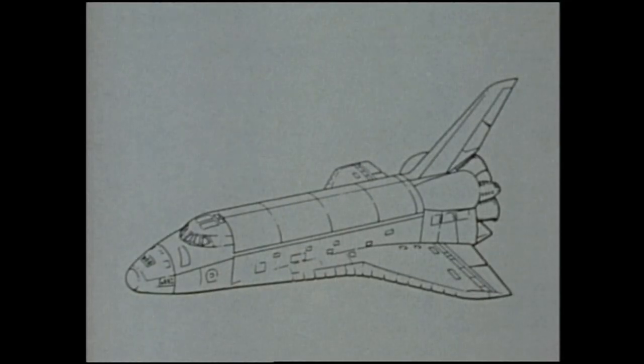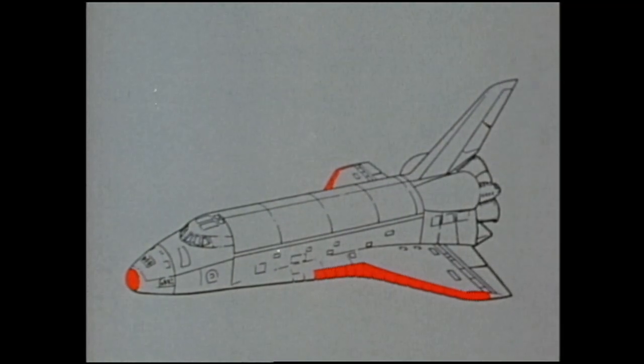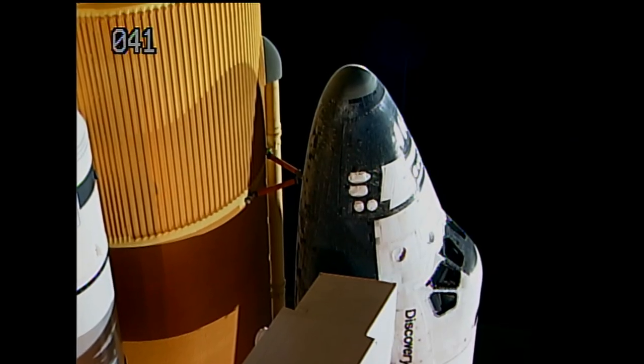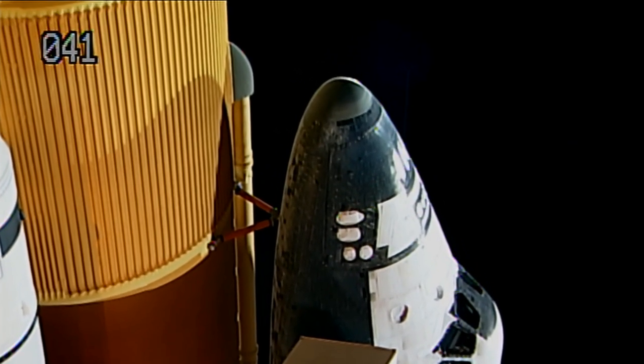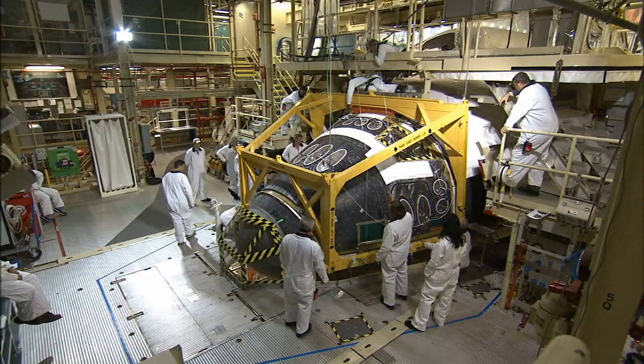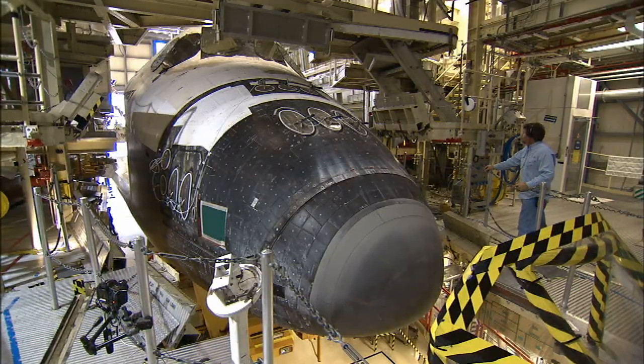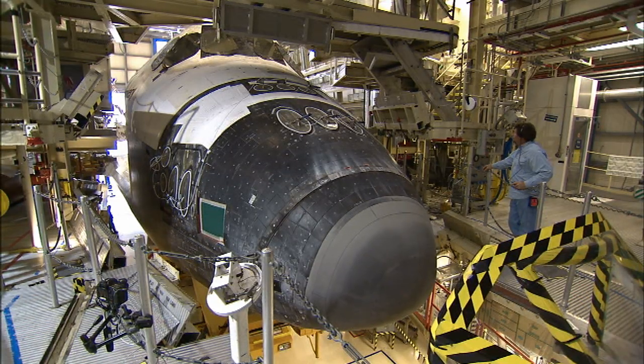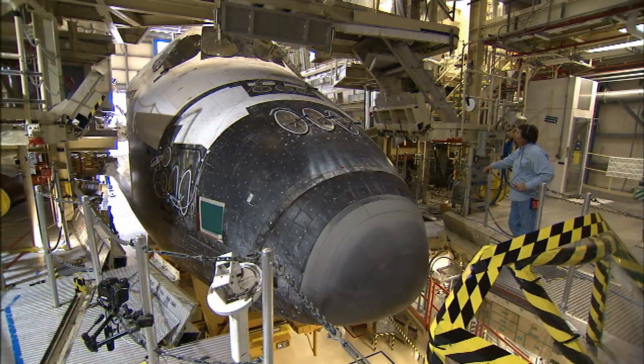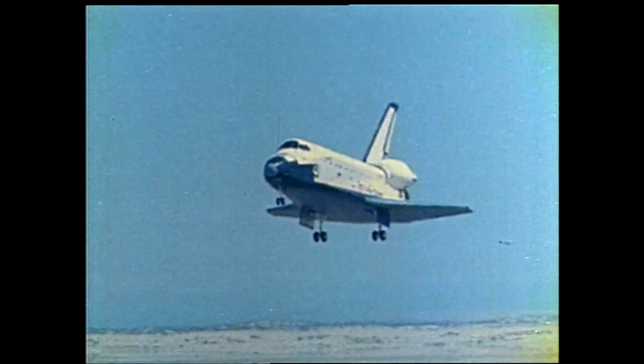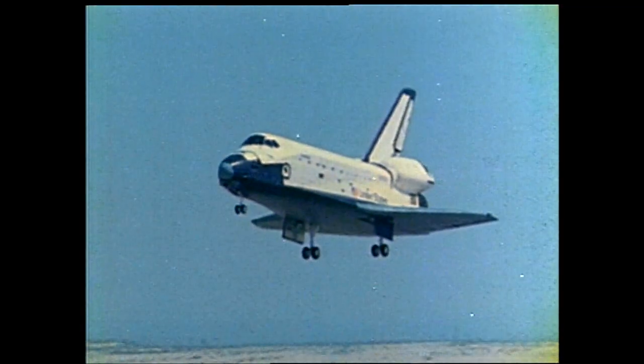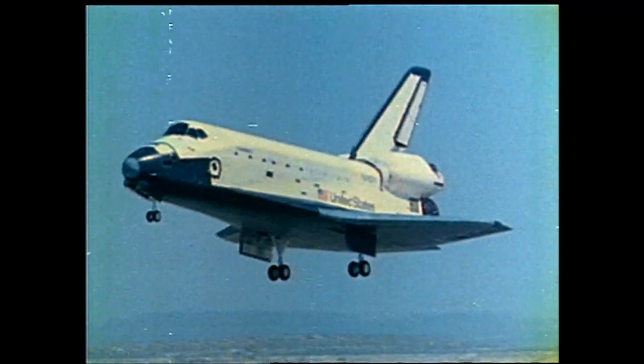Early on in the carbon program, we uncovered, along with some testing done at Ames Research Center, a phenomenon that we called oxidation between the coating of the carbon, which was a silicon carbide coating, and the carbon substrate, which is basically carbon. We had what we call pinhole formations between the interface, which was not satisfactory because we could lose the carbon coating system due to lack of strength between the coating and the carbon silicon carbide coating. That was a very important finding between Ames and Johnson Space Center in arc jet testing.